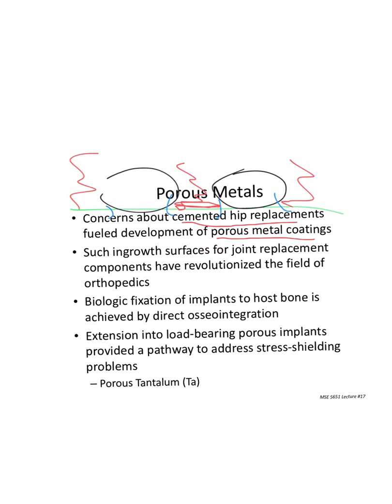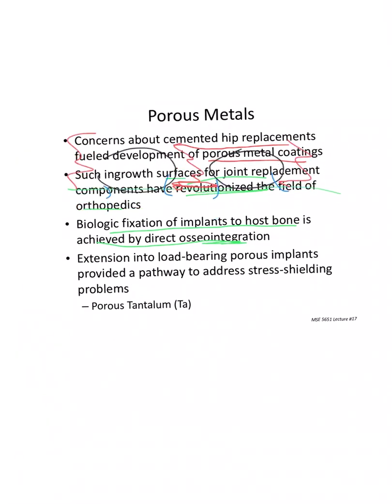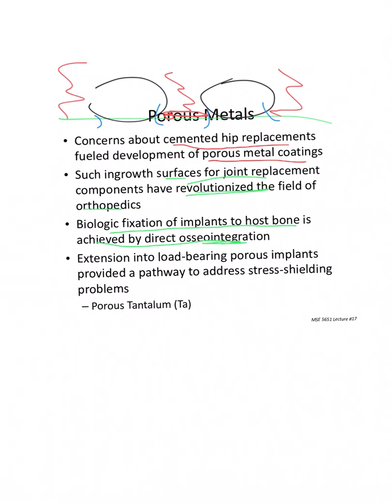And it's all very straightforward. It's just an initial process of sintering that forms those necks and gives you that coating that you want. And this is literally what it looks like in some of these products that they make. And so the idea is that these ingrowth surfaces have revolutionized the field of orthopedics. Biological fixation to host bone is achieved by direct osseointegration. There's that word again. And then load-bearing porous implants provided a pathway to address stress shielding problems involving porous tantalum. Do we know what stress shielding is?